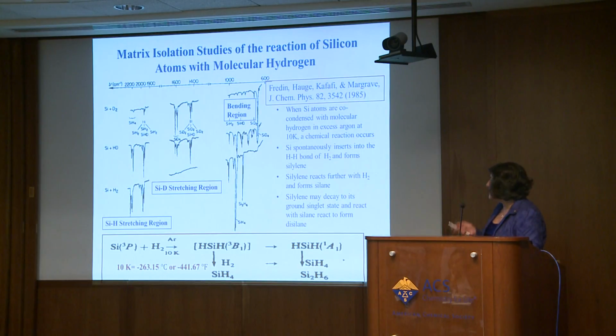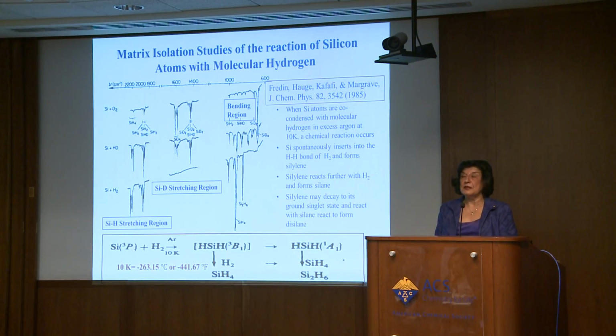So in the presence of excess hydrogen, we also saw other products like silane and disilane, which are very important products in the semiconductor industry. In order to confirm the identity of these products, because we are looking at vibrational modes, we can replace hydrogen with its isotope, molecular deuterium, and then look at the shift in the stretching vibration mode, and it can be calculated. We did confirm that it was silane, or silicon inserted in the hydrogen bond.